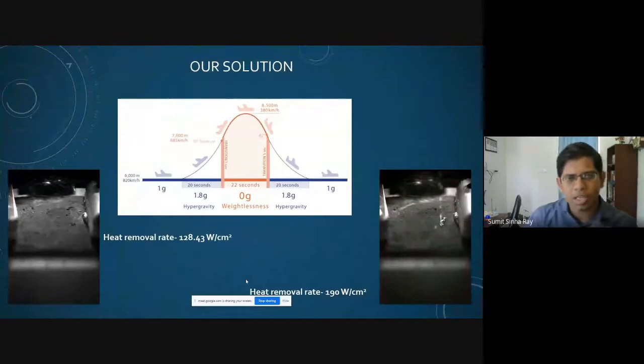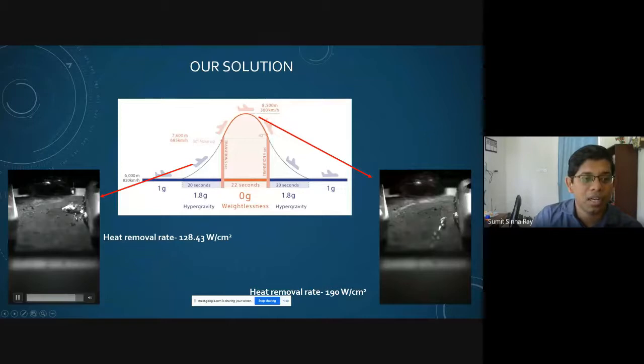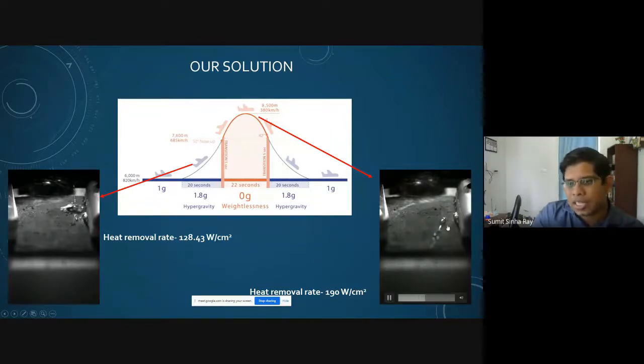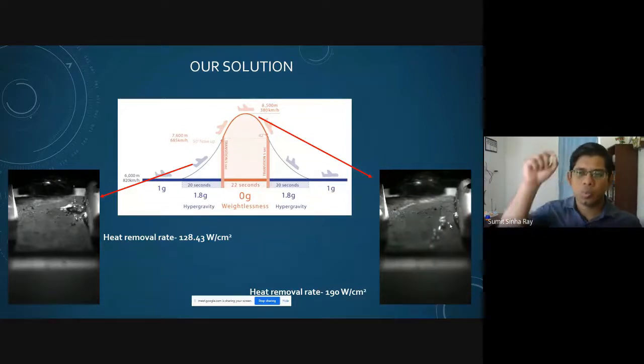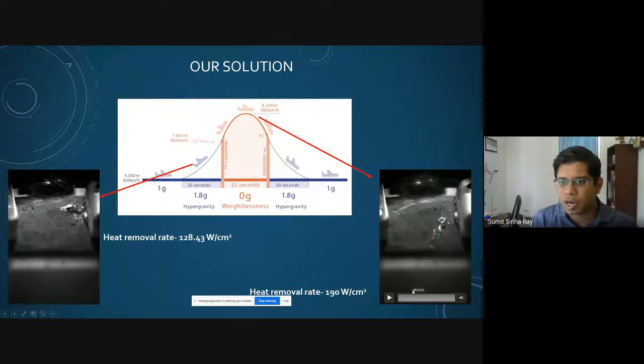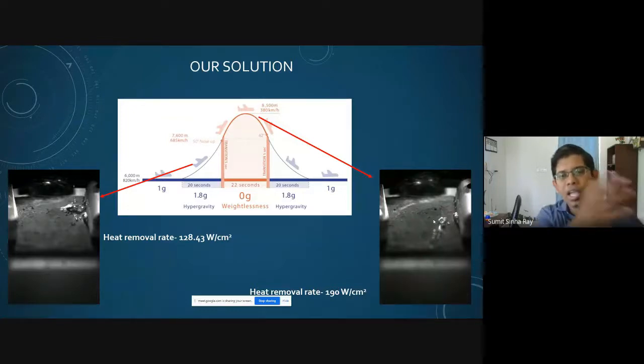During our experiment, we had these two conditions. As you can see here, this is in 1.8 gravity, when droplets were coming like a jet, and we had a heat removal rate of about 128. However, in zero gravity, we could remove about 190 watt per centimeter square. You can see that this entire situation was very difficult for issuing one droplet on a particular spot, and that is one of the reasons why some of the drops came at different locations as well. While studying it with a high-speed camera, you can see how this is boiling, and it is not leaving the surface anymore. It has been pinned onto it. It is not bouncing back and flying away.